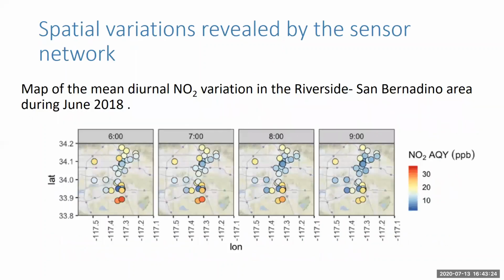Finally, if your sensor network is validated, you can begin to reveal the spatial variability of pollutant concentrations. And this shows some maps showing the mean diurnal NO2 variation in the Riverside San Bernardino area during June 2018. And it does reveal the inhomogeneity of NO2 over small spatial distances.